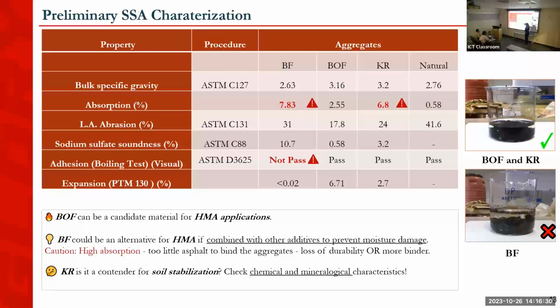So we said, well, BOF can be a candidate for HMA application. The BF slag, we saw that for a simple boiling test, we didn't see a good adhesion of the BF slag with the binder. So it did not pass, and also had higher absorption. This could be a flag that, if I decided to use BF, I need to add some additive to improve the bonding of this slag with binder. And I also have to be careful with the amount of binder that I need because there is a higher absorption of this material. It might increase the costs, right? And we can lose durability if the asphalt film thickness is not enough, right?